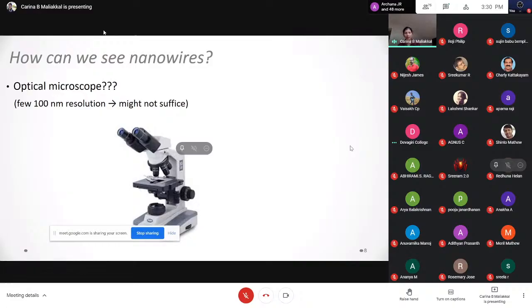If you're using that, your resolution limit would be around 200 nanometers roughly. Now if you're trying to look at a 100 nanometer or a 50 nanometer material, that thickness itself is only 50 or 100 nanometer, and if you're using a tool which gives you a resolution of 200 nanometer, that means your nanowire is just going to be blurred, you won't be able to see any features of that wire. So this might not suffice. So what is the other option?